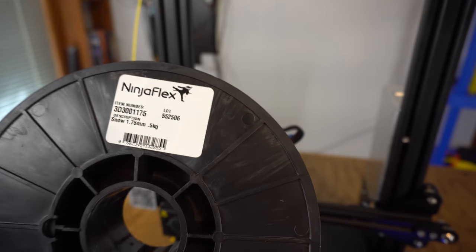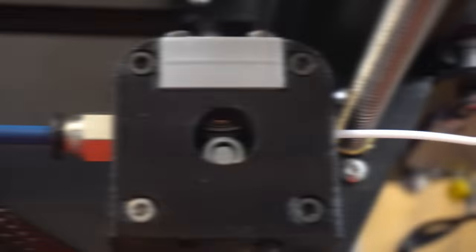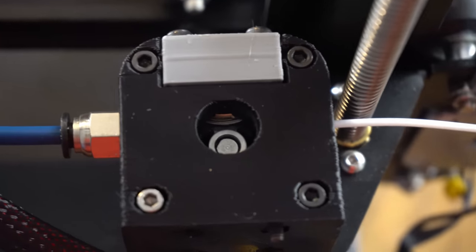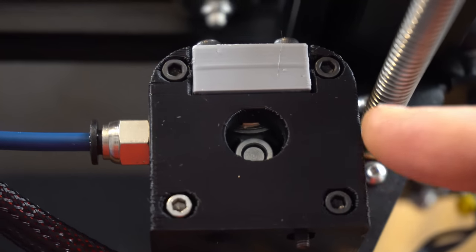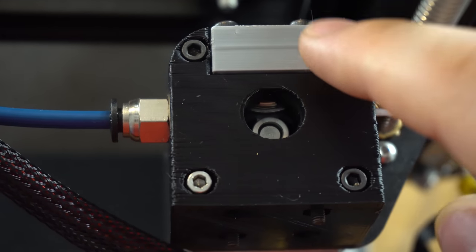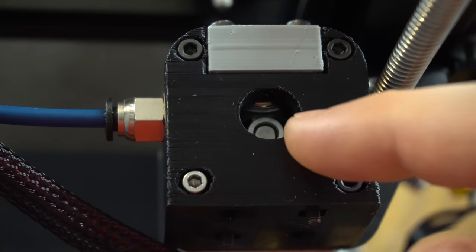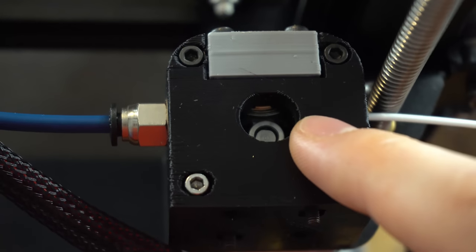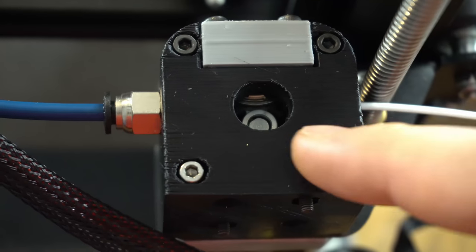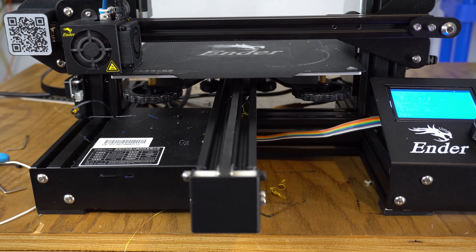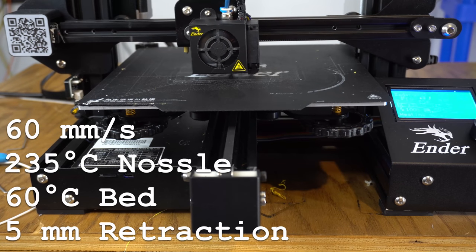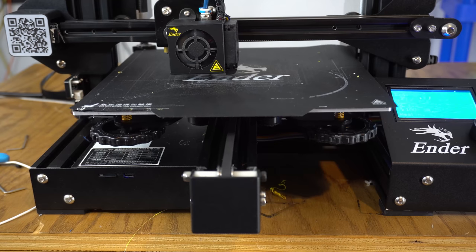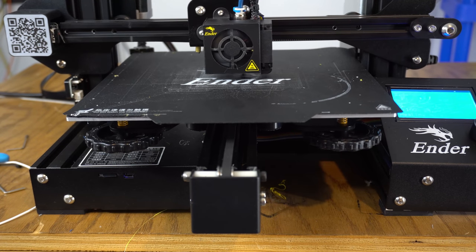All right it is time for the ultimate challenge, NinjaFlex. Let's see if we can get it to go through there. So in order to start the NinjaFlex all you need to do is take out your previous filament, heat up the nozzle and then insert the NinjaFlex right at the beginning here, allow the tooth to grab it and push it forward. You may need to adjust the tension on the upper block, either loosen or tighten it before putting it in and then give it a couple extra turns to make sure it's secured. Be careful over tightening though where you'll smash the filaments into the gear and nothing will move appropriately. Okay so we will be printing a simple calibration piece at 60 millimeters a second, 235 nozzle and 60 bed with 5 millimeter retraction. So this should not work. The recommend speeds are well below 60 but you know what might as well give it a shot.